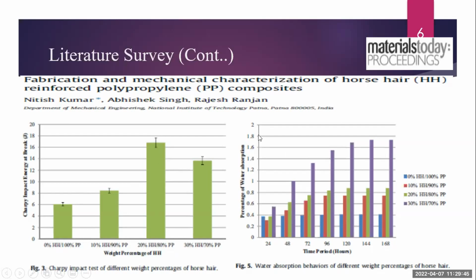Again, to check the water absorption behavior of this type of polymer composite, they submerged the sample in water for 24 hours, and they found that as the horsehair percentage increases, the water absorption also increases. So we can say that if we mix 20% of horsehair into 80% of polymer, then this sample gives the best results according to their results.